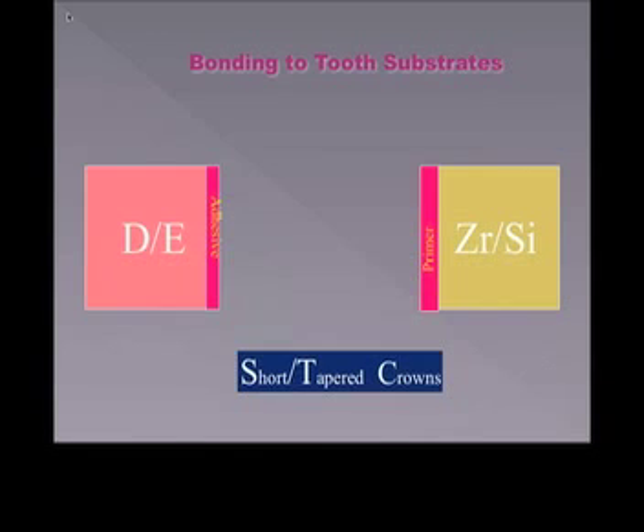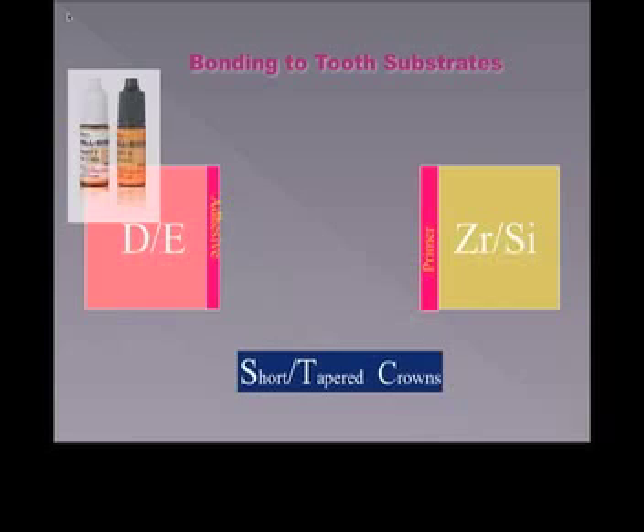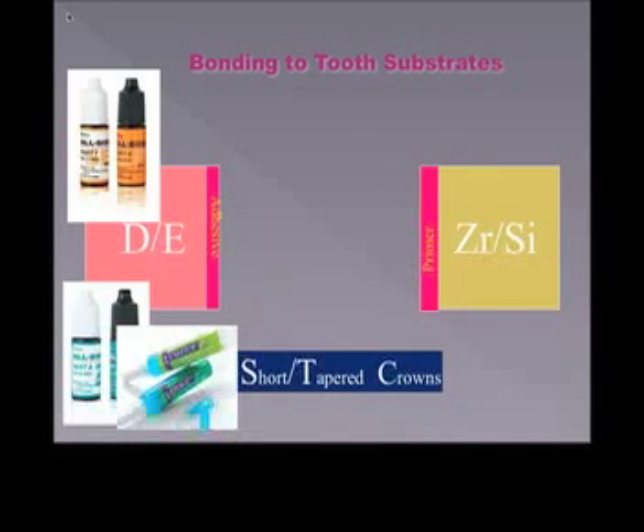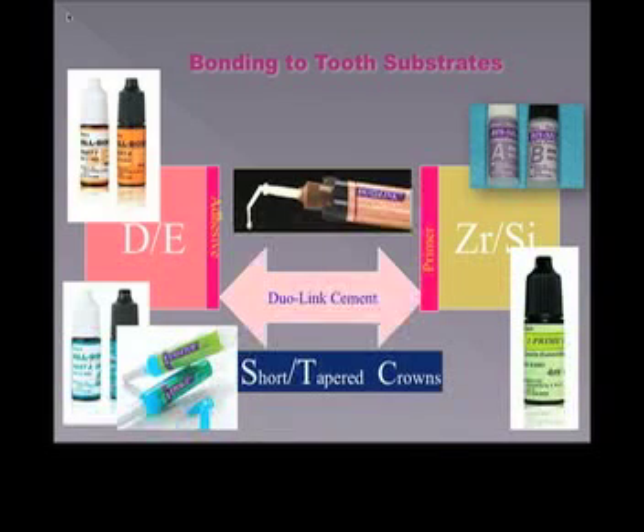Non-retentive, short tapered crowns with non-retentive design require the use of adhesive primers, either self-etch or total etch, the indirect primers, and the use of resin cement. It's interesting that BISCO recommends that for inlays and onlays, where the functional load is placed on the restoration margins, etching the enamel of the margins and using resin cement will improve the physical wear resistance.